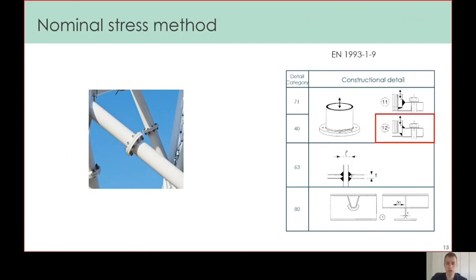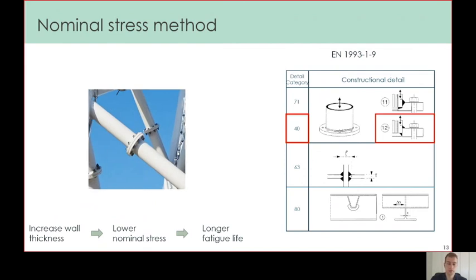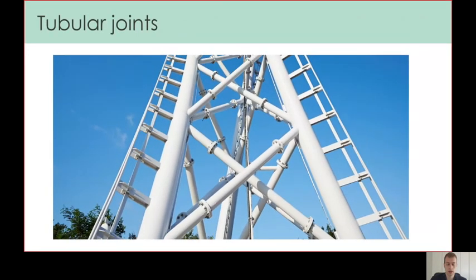And we see a whole list with structural details, and each of them has a certain fatigue strength. We call this the detail category. For this joint, it would be category 40. And if we know the nominal stress, we can now calculate the fatigue life. So you could say that if I, for example, increase the wall thickness, this leads to a lower nominal stress and therefore a longer fatigue life. So that's in a nutshell the nominal stress method.